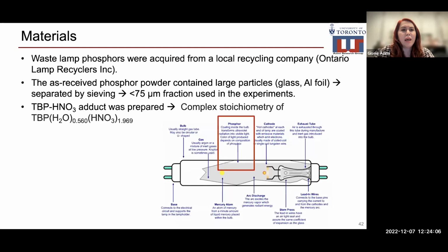We obtained the waste lamp phosphors from a local recycling company called Ontario Lamp Recyclers. The as-received phosphor powders contain large particles, mainly glass and aluminum foil, so they were separated by sieving, and the less than 75 micron fraction was used in the experiments. We used TBP HNO3 adduct by mixing TBP and HNO3 and separating them in a separation funnel and collecting the organic phase. This complex contained TBP with 0.560 molar H2O and 1.969 molar HNO3.